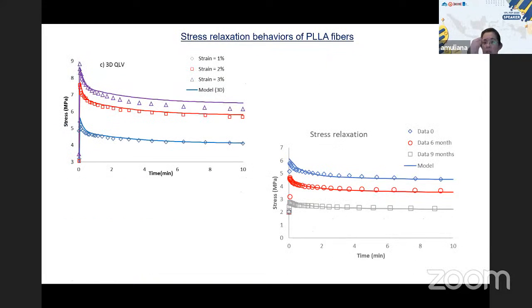Now, just to show the prediction, this is the stress relaxation of PLLA fiber at different strain levels. We see this is for only a 10-minute test. The stress relaxing, again, the solid lines are the model, which can capture the experiment. And here is also the stress relaxation after different times of immersion or degradation: 0 meaning early time, and after 6 months and 9 months of degradation, right?